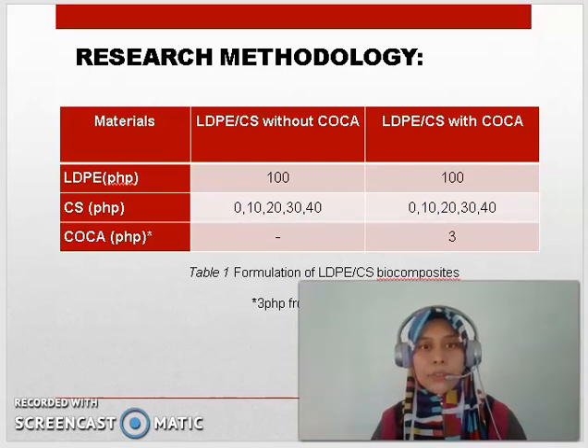For our research methodology, materials for LDPE is 100 without COCA and also 100 with COCA. CS in PHP unit is 0, 10, 20, 30 and 40 without COCA, and also the same values with COCA. And for COCA, we use 3 PHP on LDPE or CS with COCA. This table is the short formulation of LDPE or CS biocomposites. First is preparation of filler, which is CS, and then preparation of LDPE or CS biocomposites. Then we go for mechanical testing and morphology analysis, SEM.